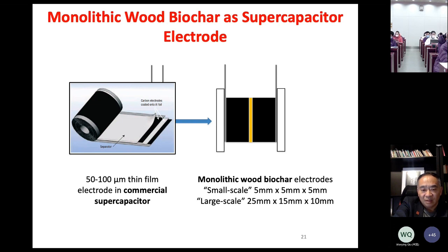Because we can make those monolithic biochar very conductive, we can actually use much thicker electrodes. And once we use much thicker electrodes, the packing density of those active materials in the supercapacitor cell will increase significantly. So this is the concept we want to test: if we can use those blocks of monolithic wood biochar to replace those thin films.